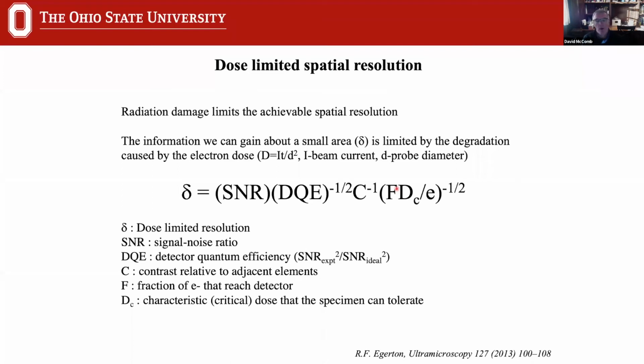And looking at the work of R.F. Egerton, we learn that one way we can think about this is that radiation damage effectively limits the achievable spatial resolution, because we can only put a certain number of electrons into an area or a volume without causing damage. And then we can spread that over a larger volume and not cause damage. So we can think about this in terms of a dose-limited spatial resolution. And that dose-limited spatial resolution delta depends on a number of factors.